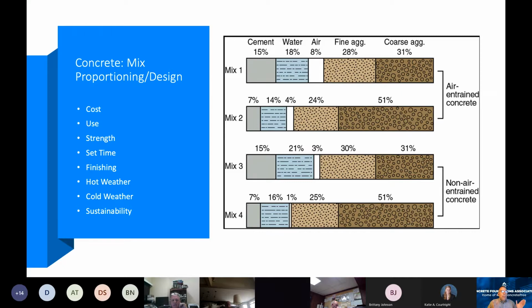Pretty soon, my 100% volume goes from 100% to theoretically 110, 115, 120% volume, and it's all being expanded by water. I'm not adding aggregate, I'm not adding sand, I'm not adding cement. Where concrete cracking comes more often than not is because of that water, because we're eventually going to take the water out of it. So whatever percentage we've got in the mix associated with water, we're going to lose. That's also in volume, dimensional change.